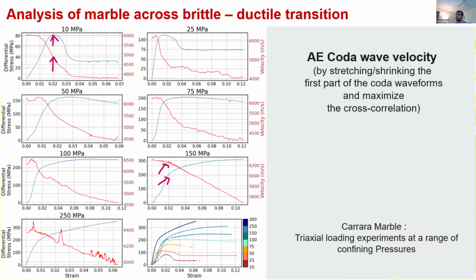So we started by saying, okay, we want to look at this, and let's start with the simplest cases and then build up complexity. So the first thing we can look at is what the coda wave velocity looks like. For each of these cases, we look at the initial arrival part of the coda, the first few microseconds, and use a stretch-shrinking method to estimate the velocity. You stretch or shrink the waveform with respect to the initial one and find the maximum cross correlation to find small shifts in the velocity. We've tried a few different methods using spectral approaches also, and you basically get very similar results.